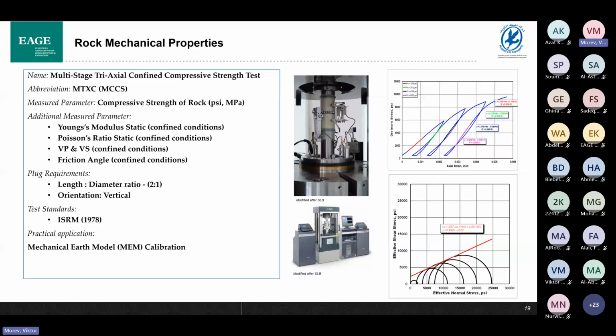It can be single stage or multi-stage. Here on the slide you see the multi-stage triaxial test. The rock sample is tested under confining pressures, which represents the subsurface conditions more realistically. In a multi-stage approach, the same sample is loaded at different confining levels, and you see them on the top right plot. From this response, we can derive not only strength and elastic properties like from a single UCS test, but also the friction angle and failure envelope.